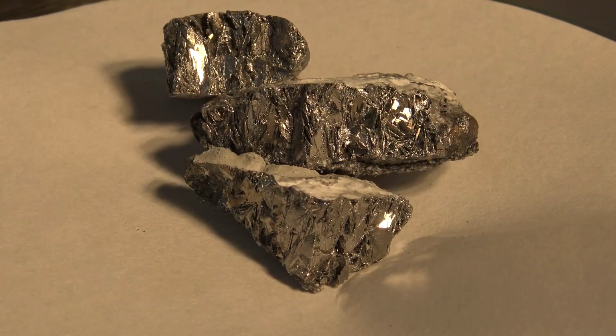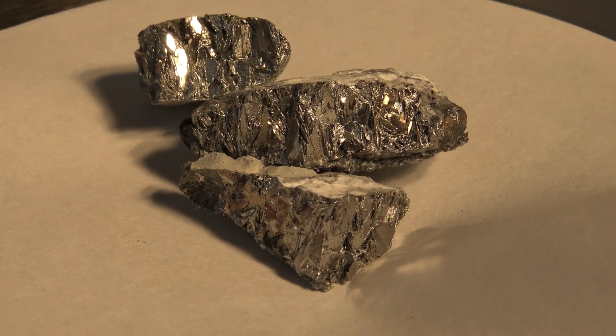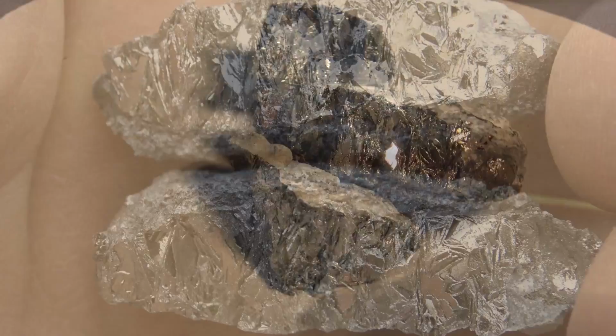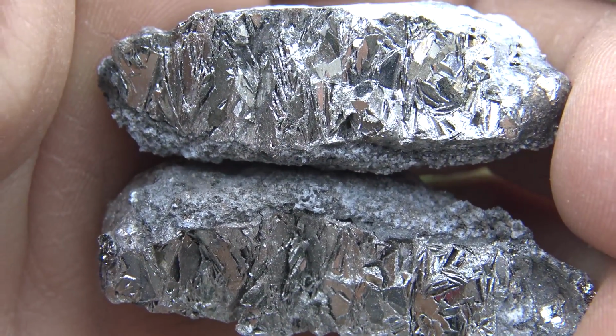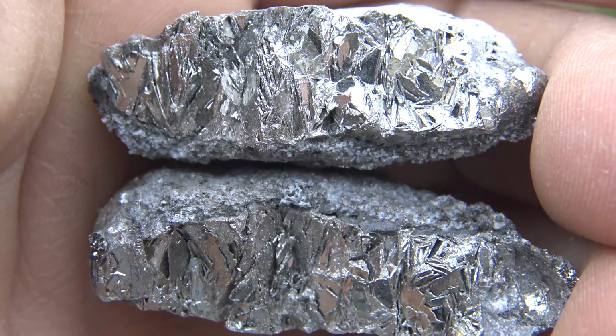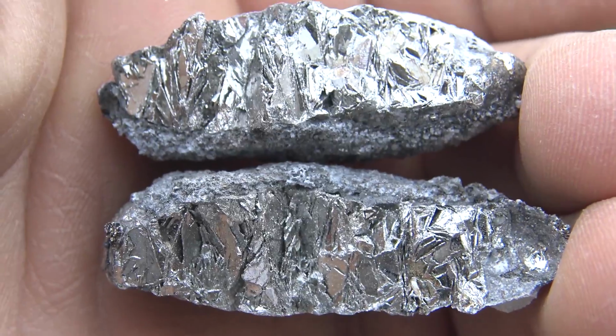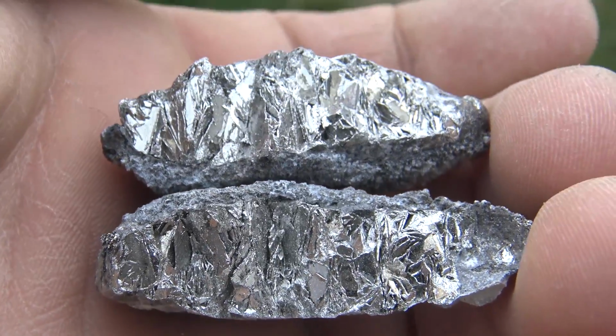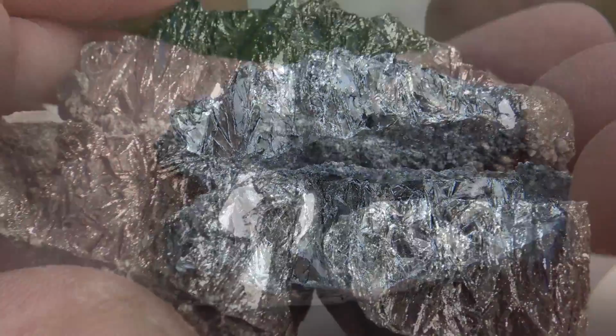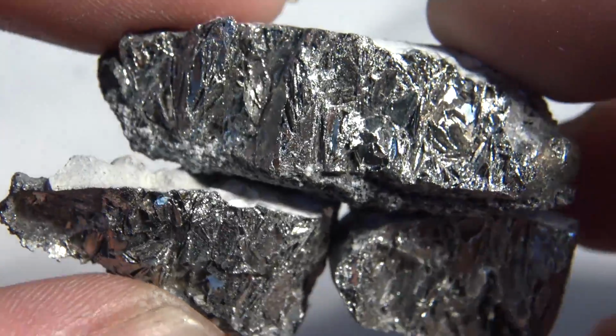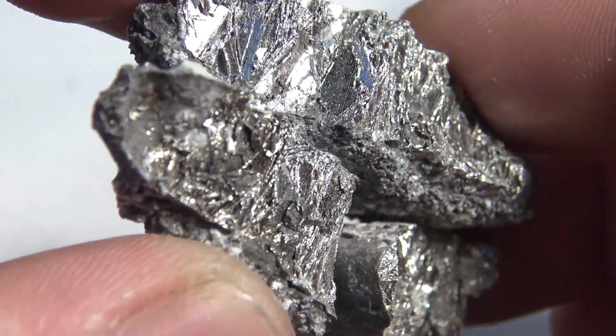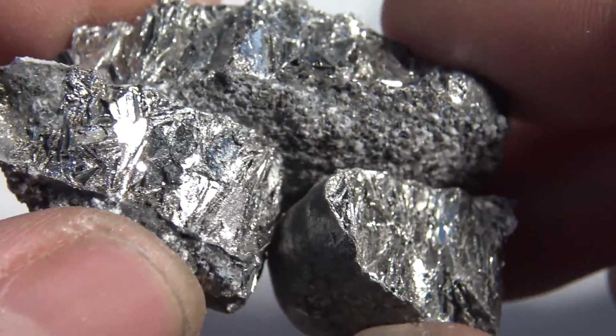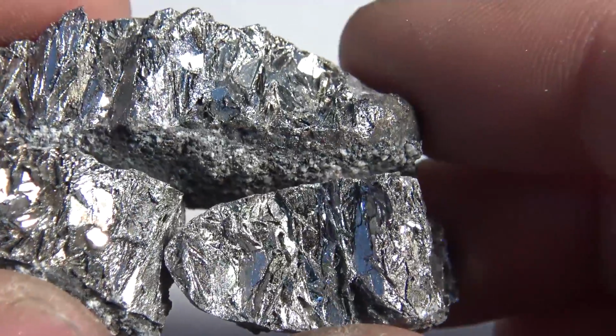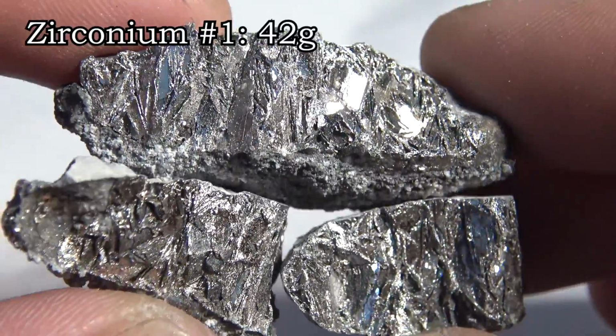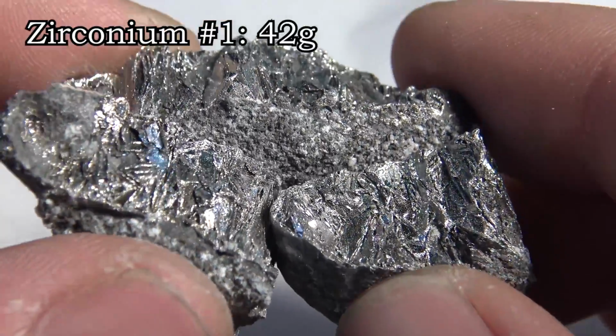The zirconium, on the other hand, well, it extracted for sure, but why it extracted the way it did, I have no idea. According to Amazing Rust, when he had a sample of the titanium he extracted using the same formula analyzed for purity, it came back that there was a large percentage of aluminum with the titanium. So is this what pure zirconium crystals or crystals of some zirconium aluminum alloy look like? Either way, it's impressive, I think. Coming in surprisingly light at 42 grams, the yield for this formula isn't very high at all.